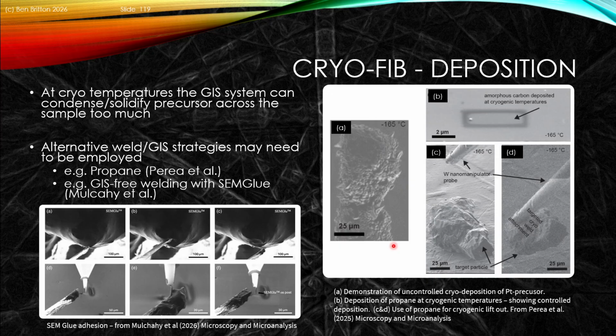One of the challenges, however, at cryogenic temperatures was noting that if you are trying to do cryogenic deposition, you get condensation of the organic precursor across the sample, and so you get this mess on top of your piece. Now there are a few different ways that people solve this. One example is a suggestion, and this is very emerging, but effectively use of a different cryogenic gas for this. And in this example, it's the use of propane, as suggested by Perea et al. in here. And so that lets you have a targeted deposition. This was done at minus 165 degrees C.